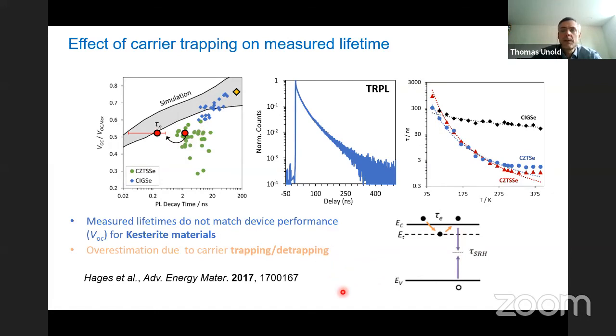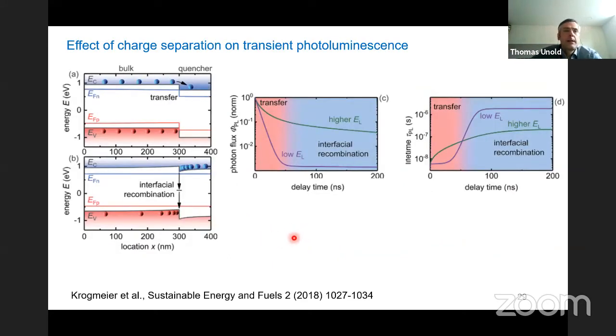And this is also something you really have to watch out for, especially if you have discrepancies between your measured JV performance or your PLQY and your lifetime. Another aspect that of course is important is charge separation in transient photoluminescence and maybe also in quantum efficiency measurements. So shown on the left side is a simulation taken from this paper from Krogmeier et al.